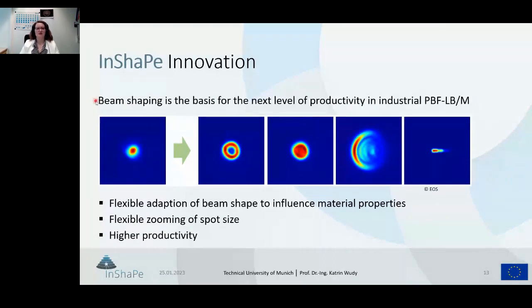So the innovation here is that we are able to shape our beam, our energy input, in space. On the left-hand side in this picture, you see the typical Gaussian energy distribution, which means a really high energy in the middle, and in the outer area, the energy is decreasing. This is a top view. If you would have a side view, you would have this typical Gaussian shape. What we are able to do with our novel optical module is to change the size of the spot, but also the shape, so the picture we are projecting on the powder bed surface. Here you see one picture, which could be a donut profile, for example, or a top hat profile, but there is also the possibility to create these C-shape profiles or line profiles. Actually, you can create any profile you can imagine.